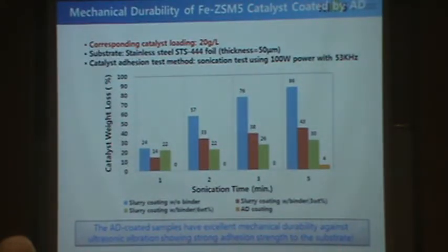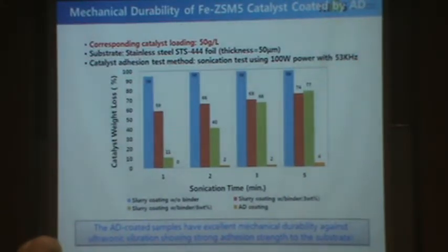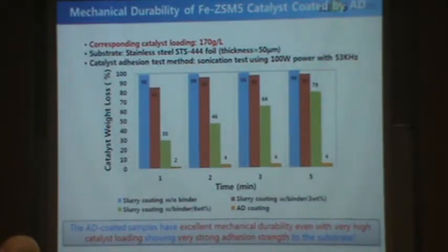Similar one, but slight loss of our catalyst. Corresponding catalyst loading 50 grams per liter. The amount of loss a little increased, but still very low relative to the conventional wash coat. So most of the wash coat remained after the heavy test using the ultrasonic tester. Corresponding catalyst loading 170, which is a typical loading for automobiles, especially TWC. And we still had a very good adhesion.